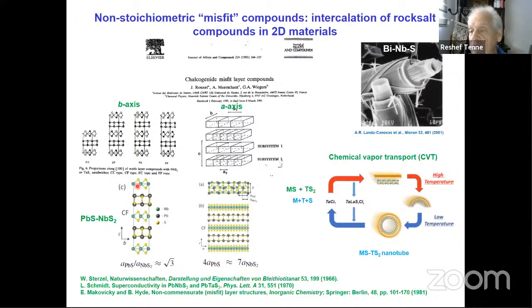I won't go into the details, but just say that these are called misfit structures because there is a misfit. Along the a-axis, the rock salt and the tantalum disulfide or niobium disulfide do not agree, and they are incommensurate. Consequently, you don't have a real unit cell in these structures. But nevertheless, they form layered compounds, platelets.